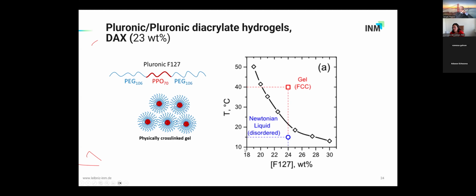and these are thermoresponsive. The transition temperature at the concentrations we work, around 23%, is around 15 degrees, or 15 to 20, no, here it is 22, but this depends also on the molecular weights, but it's below room temperature and below also body temperature. So you can process them below that temperature as a fluid. You can mix them with the bacteria, and then you can let them solidify and form a physical hydrogel at body temperature, or afterwards at room temperature as well.